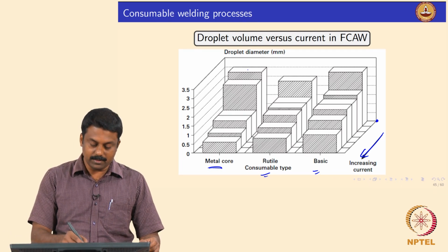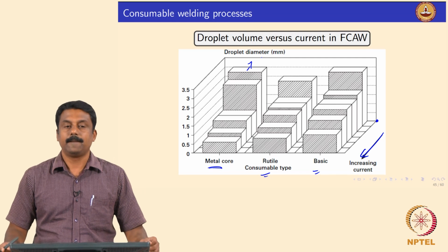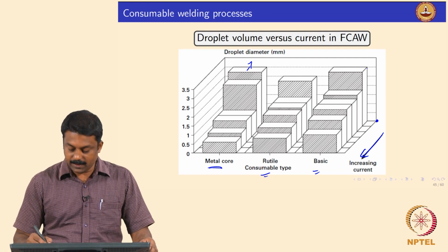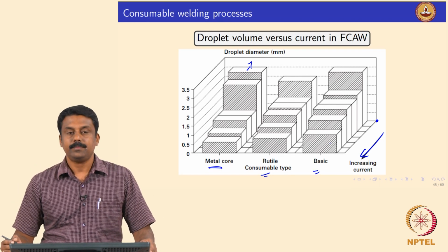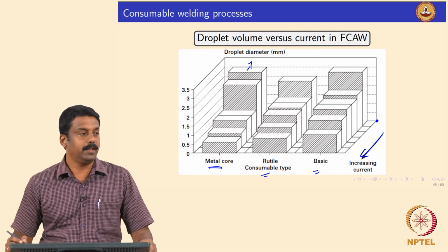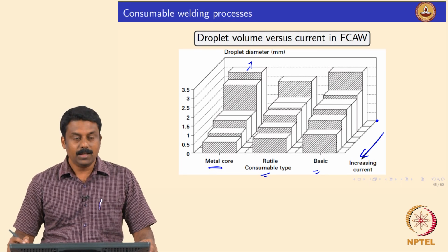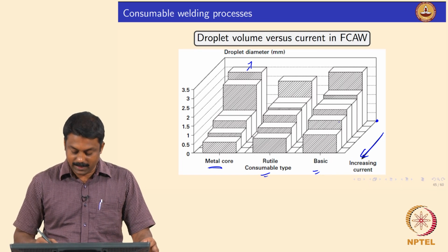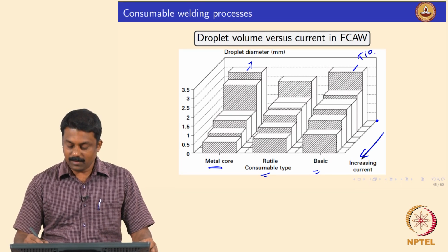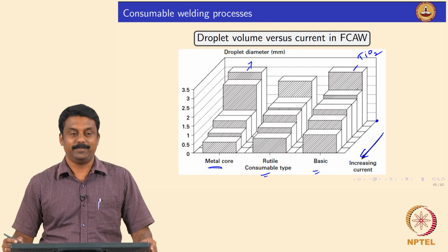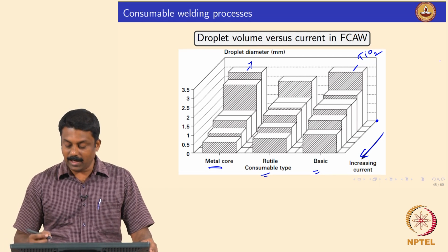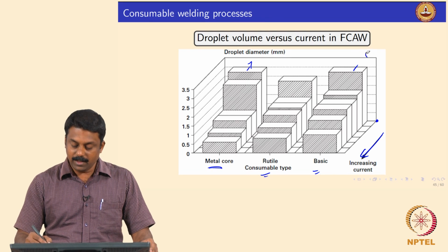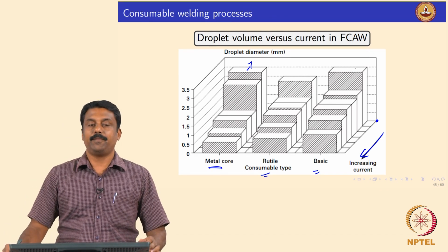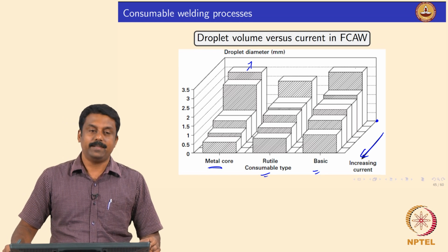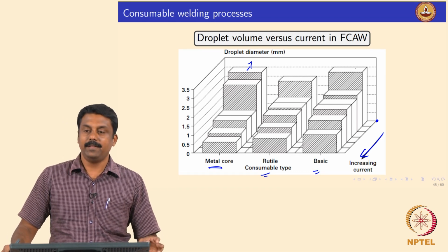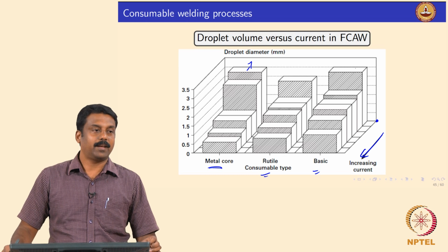whereas in basic and metal core, obviously this also contains basic fluxes, where in basic fluxes the droplet diameter will always be higher. Yes, it's clear. Then what needs to be done? We see you can't add titanium oxide to this, so then you will also generate hydrogen, right? So we can think about adding some other fluxes which can favorably change the surface tension. For example, fluorides. Okay, so fluorides or silicates that can be added.